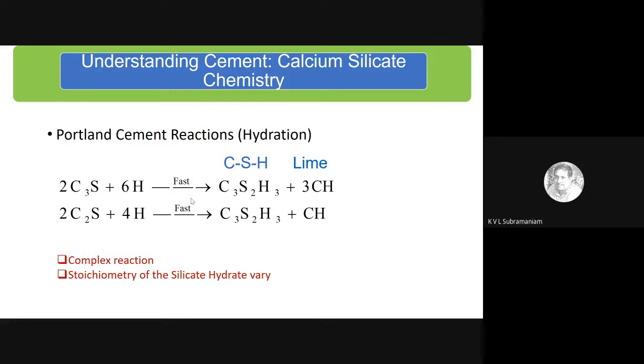Now, this is a very simplistic representation of the chemical reaction. To this date, we don't know the exact stoichiometry of calcium silicate hydrate. It's very variable. It basically changes depending on different conditions like temperature. It also varies within the cement paste. It will vary depending upon the location at which you sample the material. So the CSH is not a fixed material. And usually when we give this composition, it is given in an average sense. So whatever you see in the chemical reaction written here is in an average sense.